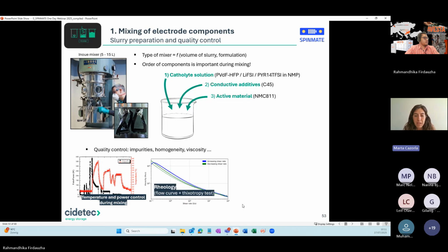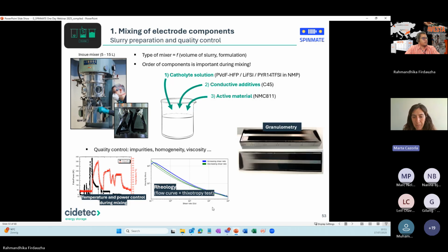And also, once we have the slurry, the mix itself, we do some rheology. We monitor the flow curve and thixotropy test. It's important for the slurry to be viscous, because we don't want all the components to precipitate, as this will cause heterogeneities in our slurry. We then check the presence of aggregates. This is called granulometry. It's basically putting a certain amount of this slurry on a grindometer, in which we can measure the size of possible aggregates present in the slurry.